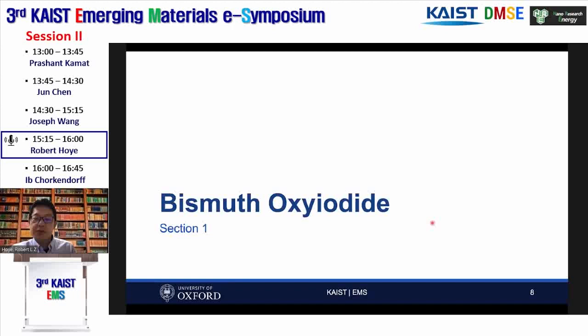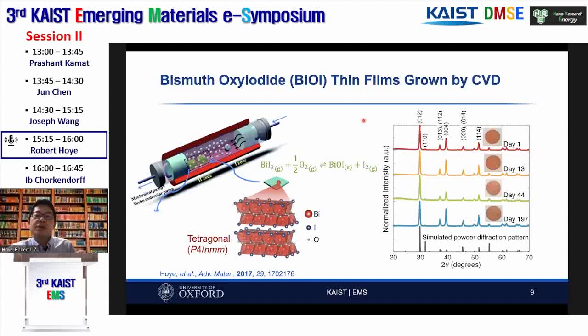This is not a material you would have thought about if you're just looking for a lead-free perovskite, because it doesn't have a perovskite crystal structure, and it's not chemically analogous to the perovskites either. But the reason why we're interested in this material is because it's electronically analogous. You can see the crystal structure over here. It has a layered structure with 5 atoms throughout the cross-section. And at the band edges, it's mainly composed of bismuth and iodine states in a very similar way as what you would find in the lead halide perovskite.